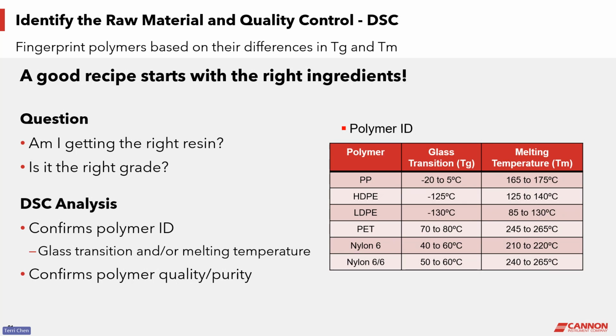DSC is probably the most commonly used thermal instrument in polymer characterization. DSC analysis is typically used for identifying the raw material. A simple DSC temperature scan can tell you if this polymer resin is a polyethylene, polypropylene, or a PET resin. DSC identifies polymer IDs based on the differences in their glass transition and melting temperature.